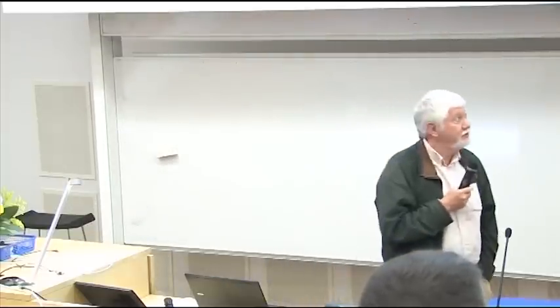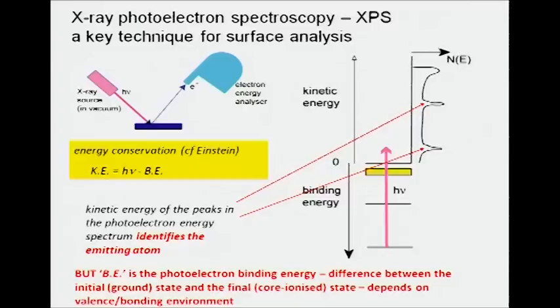Of course, we've got this little energy equation here, and the question is, what is BE? What is the binding energy? The binding energy, of course, is the thing you measure by this technique, i.e. it's specific to the way you measure it. And that's the interesting bit, because it does vary according to the valence environment of the atom, although it's a core-level species, and the binding energy is largely characteristic of the element. There are small variations depending on the local bonding valence environment, and these are the so-called chemical shifts, the core-level shifts that Niels has been talking about.